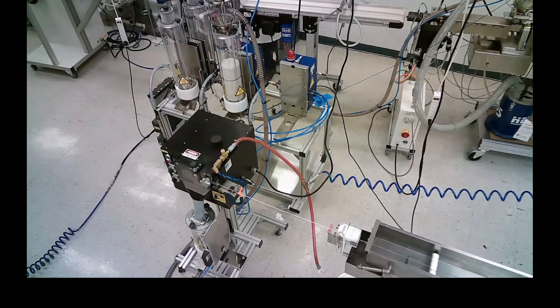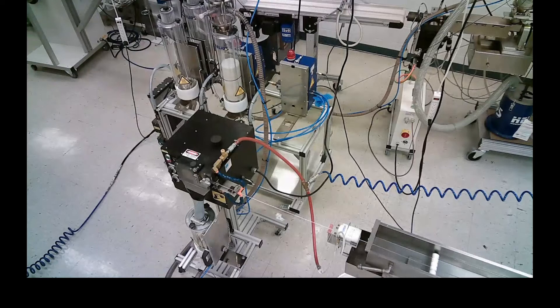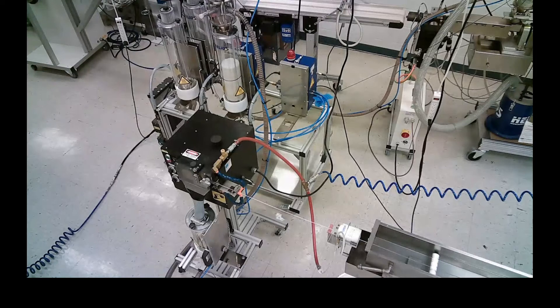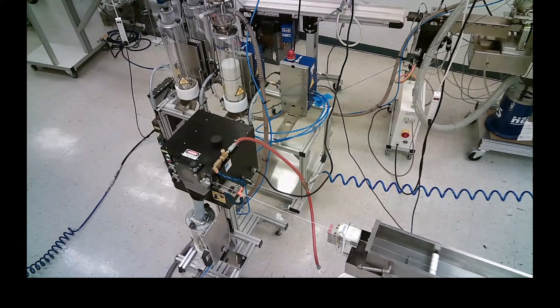They do everything with hot air and obviously they convey the material then in our setup into one of the reservoirs in between. They will dry the material as it continuously is going to be transported into our single screw line where we can with the help of a melt pump create the exact diameter or dimensional shape and form of the filament that we are going to wind.